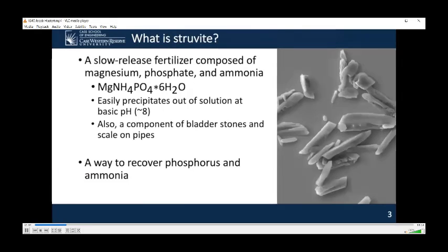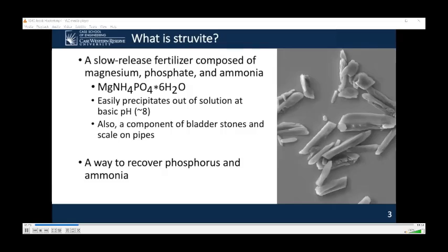Struvite is one of the ways to recover phosphate from wastewater streams. Struvite is a slow-release fertilizer composed of magnesium, ammonium, and phosphate that precipitates readily out of solution at basic pH. Magnesium and ammonium are also valuable components of fertilizer, further adding to struvite's value. The slow-release character is valuable because it allows for lower amounts of phosphorus runoff. However, struvite can also be viewed as a nuisance because it is often found in alkaline streams of wastewater treatment plants where struvite growth can occlude pipes and cause damage.